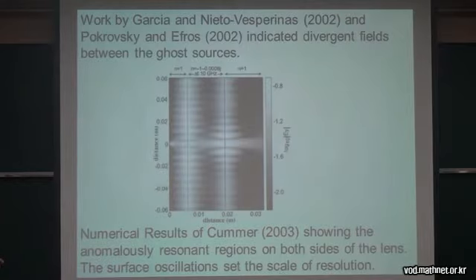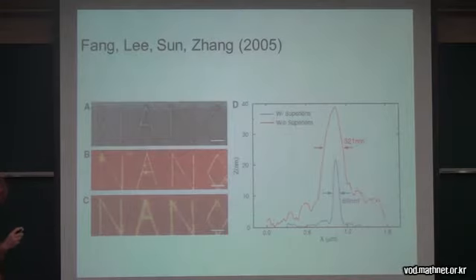And this is numerical results of Cummer showing that these regions here, these are called surface plasmons, but they're basically what we call anomalously resonant regions on both sides of the lens. And it's actually the length scale of these surface oscillations which sets the scale of resolution, not the wavelength of the light or the radiation that you applied. And Fang, Lee, Sun, and Zhang in 2005 experimentally demonstrated that these could resolve finer than the wavelength. And so this is the word nano, which is inscribed. This is the resolution using the superlens, and this is the resolution without the superlens, actually. And so actually you end up with a peak of width 89 nanometers, as opposed to without the superlens of 321 nanometers, and this is sub-wavelength actually.